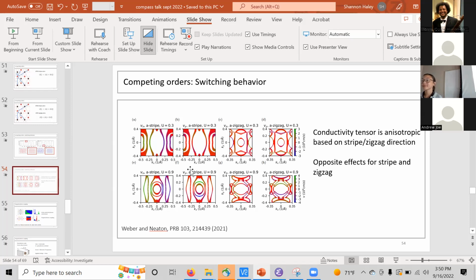In your sample, you have the distinct color finding. Oh, you said they're all... that's right. Yeah, I think that with the off stoichiometry, like the disordered samples, maybe there's a little bit more room for there to be some canting within the plane. At least from looking at some other measurements that we've done, but not all that much. So that's actually something we were looking at for a while. We just saw that we introduced disorder, now we get the switching, we have the perfect sample, the switching is basically gone. We thought for that reason that this in-plane component was really important. But now we know that even with the disorder, it's still pretty small.